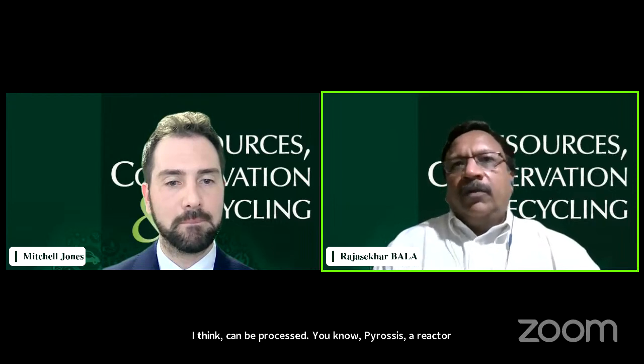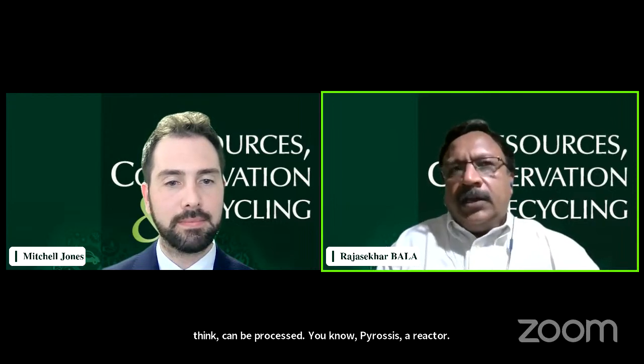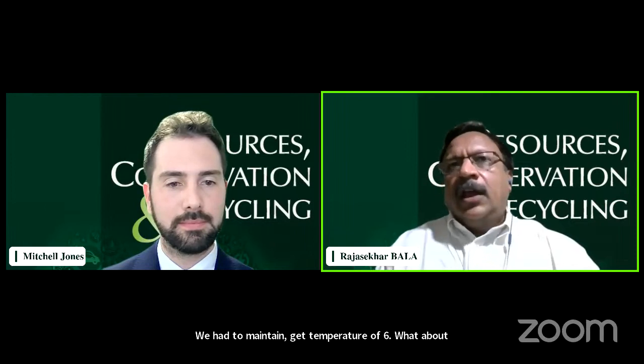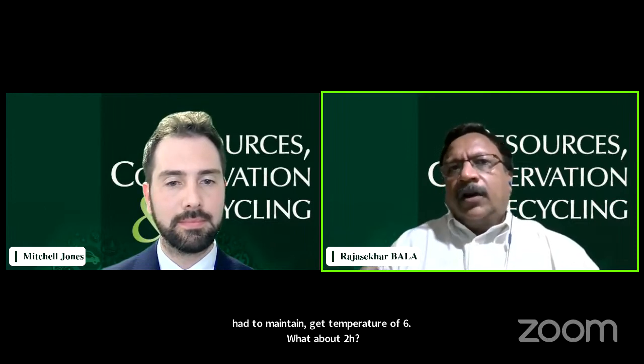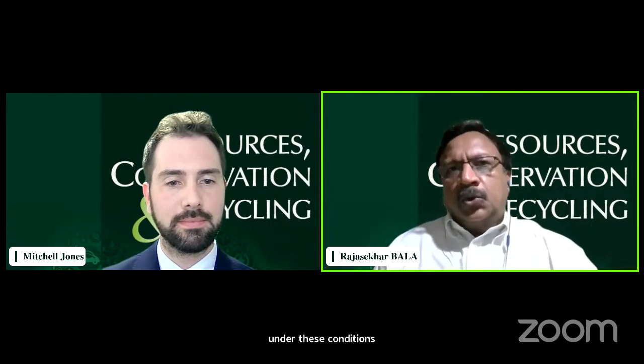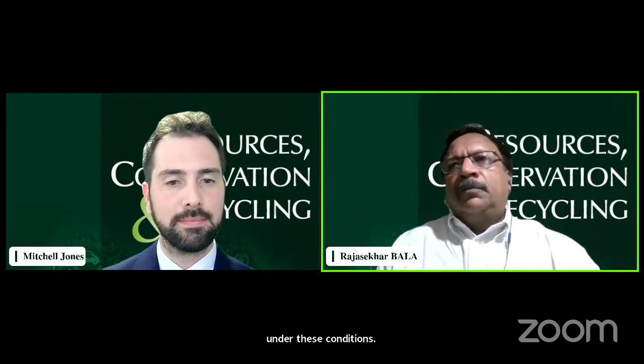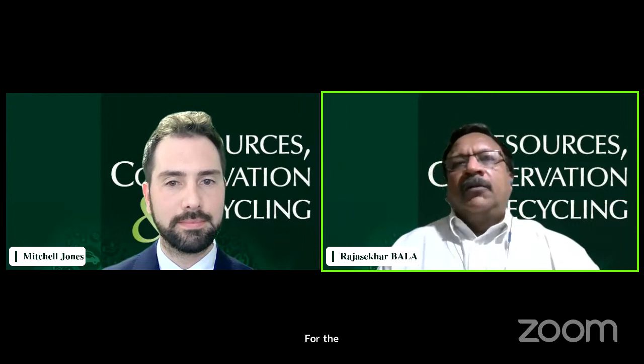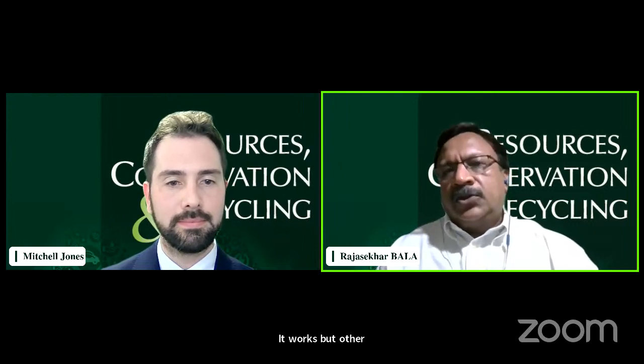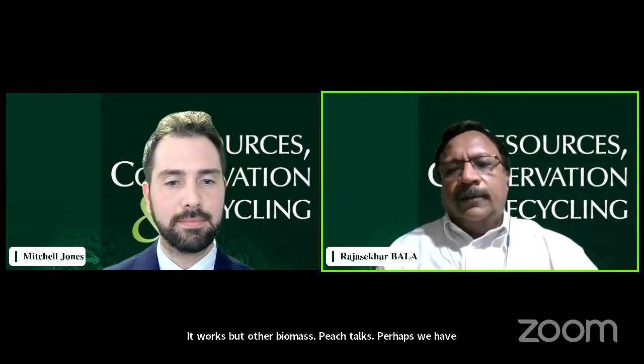And likewise, when you do pyrolysis, we have to maintain a temperature of 600 degrees Celsius for about 2 hours. So we have tried to optimize the experimental conditions. Under these conditions, for the biomass feedstock that we have used, it works. But for other biomass feedstocks, perhaps we have to do even more optimization and process control.